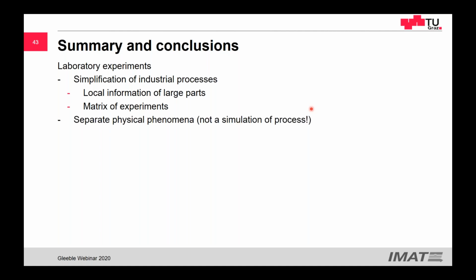We use the laboratory experiments also to separate physical phenomena. And this is not the simulation of the process. So sometimes we quench very fast and we cool down very fast, or we go to very large deformations. This is for the industry itself not interesting. We cannot go that fast in the cooling rate. But this is important for understanding what happens at every single step with the material. What happens during the formation, what happens during cooling. So we can really separate all these physical phenomena. And sometimes we can't. But this is why we do the laboratory experiments.